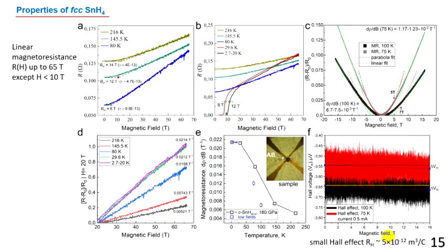We also studied transport properties of tin tetrahydride in high pulsed magnetic fields up to 65 Tesla. And we found that linear magnetic resistance dominates in this compound. Only in very narrow area of magnetic fields below 10 Tesla we can use parabolic fit to describe the behavior of magnetic resistance. We also measured Hall effect in this compound at two temperatures, at 75 and 100 kelvins, and I found that the Hall effect is pretty small.